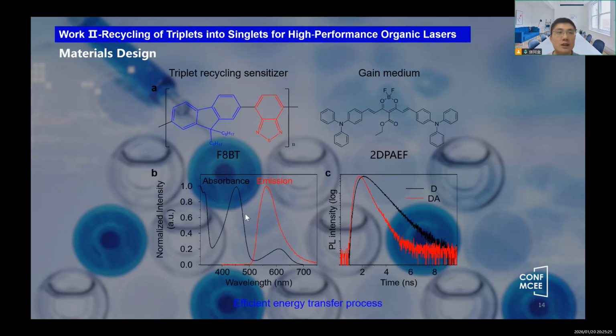First, regarding material selection, the large overlap between the sensitizer emission and the gain media absorption spectrum, as well as the change in sensitizer lifetime before and after doping with the gain media, confirm the existence of an efficient energy transfer process between the two, enabling the above-mentioned excitation process.